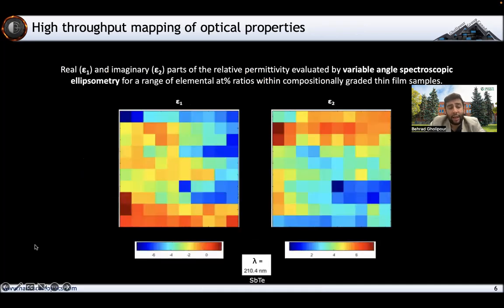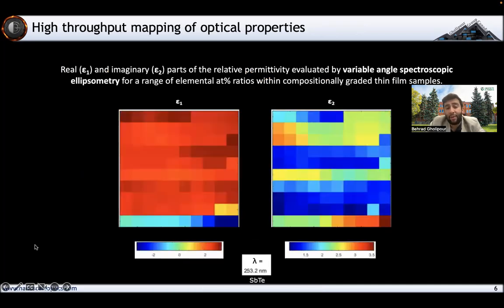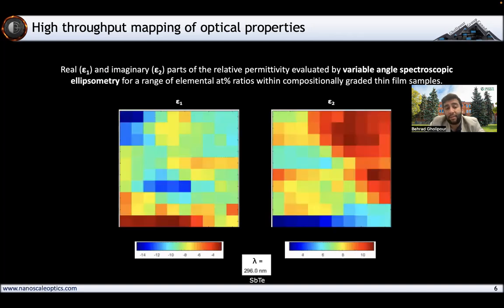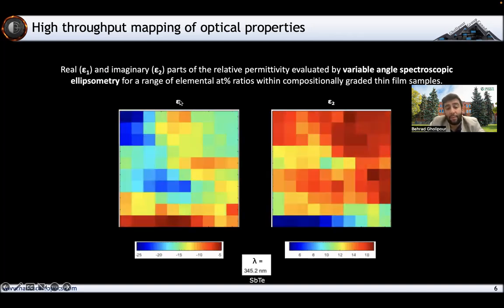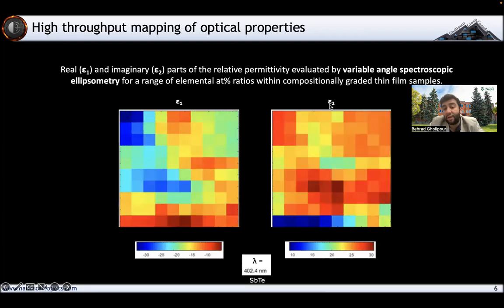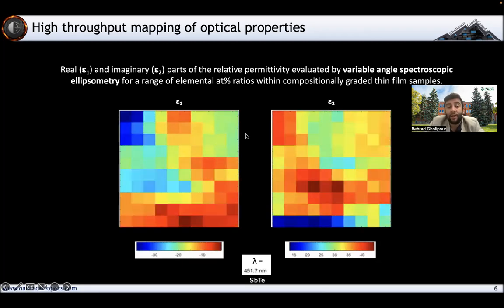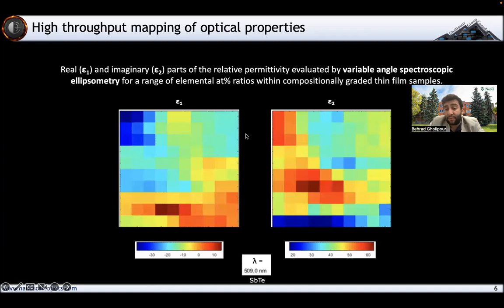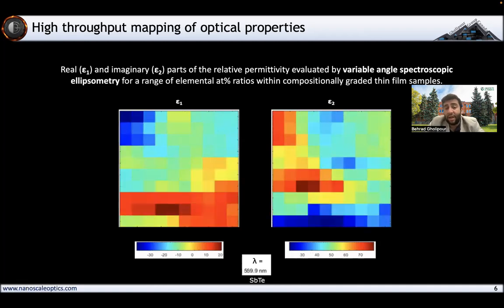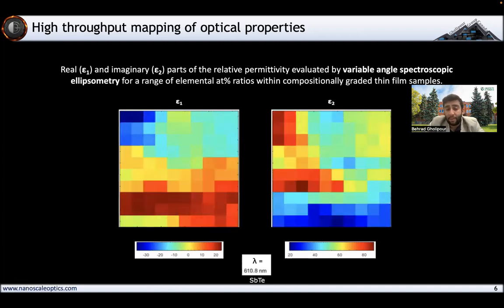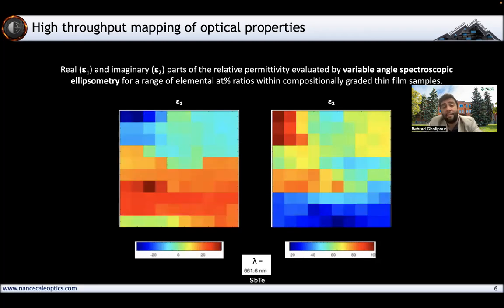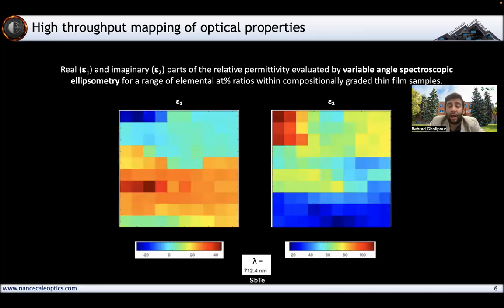So I show you here a variable angle spectroscopic ellipsometry measurement of one of these samples. It shows the real part and imaginary part of the dielectric function, the permittivity, if you will, which determines for us our refractive index. In the case of photovoltaics, this is very important for our absorption levels. And in the case of computing, it allows us to understand how we can integrate these with different waveguides and different optical fibers.